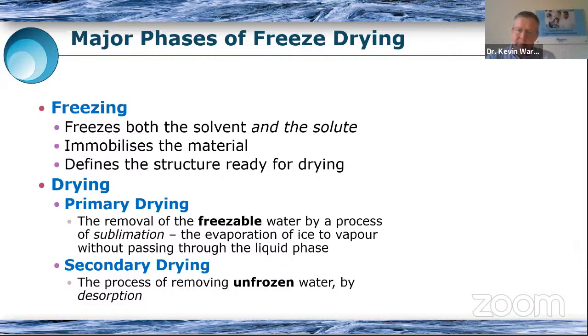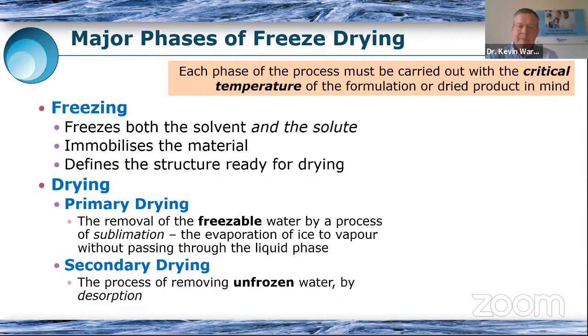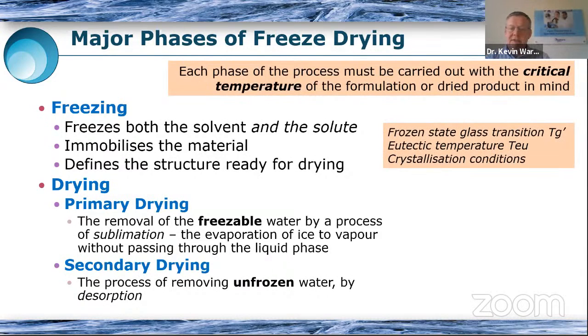Now, in order to do that successfully, we need to take into account during each stage of the process various critical temperatures. And these can vary depending on the type of product, the type of formulation, ingredients that we have. So in the frozen state, we're primarily concerned with the frozen state glass transition temperature for amorphous materials. Now, of course, most of the biological materials we will encounter will be at least largely amorphous, at least partially amorphous. So if we've got proteins, sugars, antibodies, polymers, and other stabilizers, maybe amino acids, then these will typically be amorphous. And so we will be concerned with the glass transition.